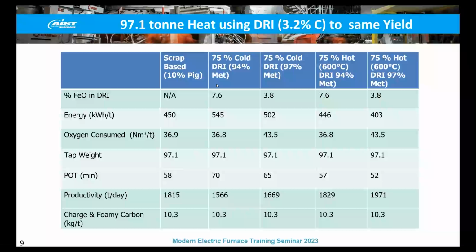So if you're adding cold DRI to the furnace with a low metallization, you're seeing a fairly significant increase in electrical energy.